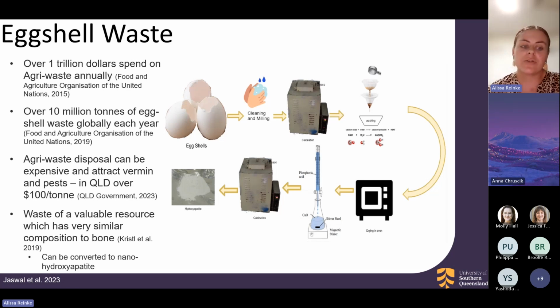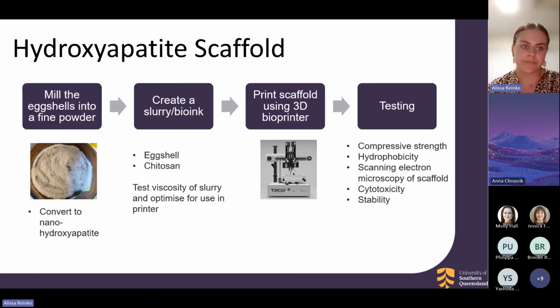Now, eggshell has a very similar composition to bone, so it's a valuable resource in this space because I am able to use it to replicate the calcium composition of bone, but I can also convert it to hydroxyapatite, which is part of the bone that gets very hard, and use that as a product to actually make the scaffolds. I am also combining eggshells with chitosan. So chitosan is the compound that is found in crustacean shells. You can also get it from fungi, but you're probably more familiar with the solid shell of crustaceans. And combining that with eggshell will create the strength to replicate bone within the model.